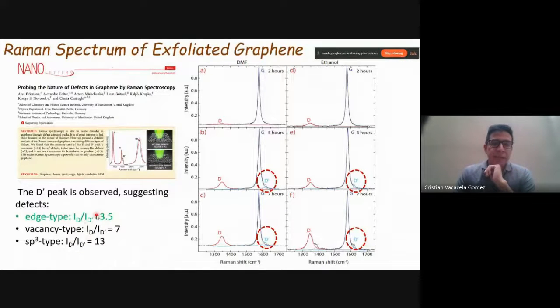For example, here, if you take again the ratio of just the intensity of the D peak over the intensity of the D prime peak, you can have different numerical values. For example, if you have 3.5, you are working with edge-type defects. So you have different defects at the edges in the plane of your graphene system. And also, if working with a similar approach the ratio gives the value of 7, you have the vacancy-type defects. If your number is greater than 10, like here 13, we have sp3-type defects.